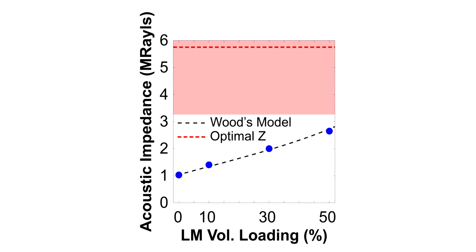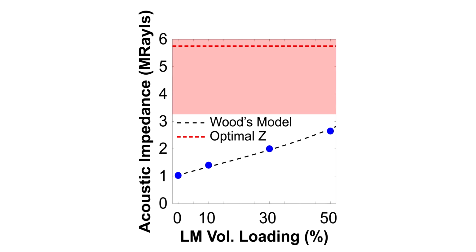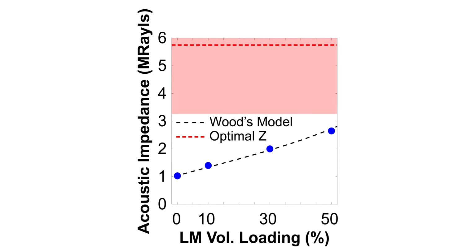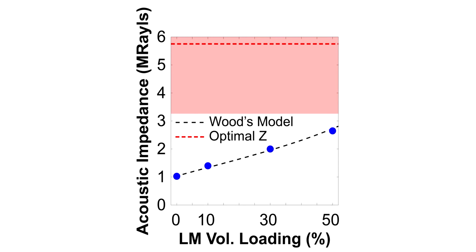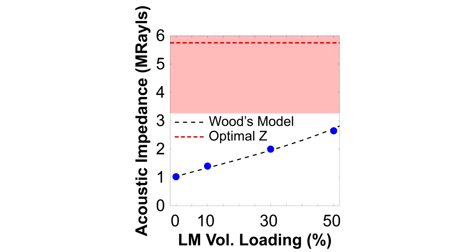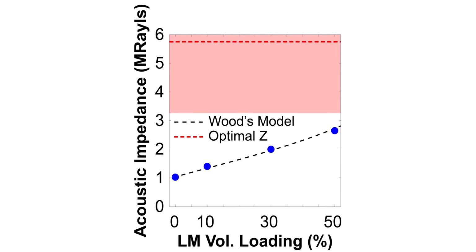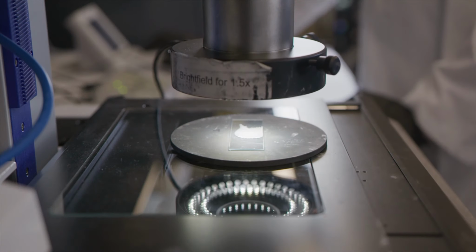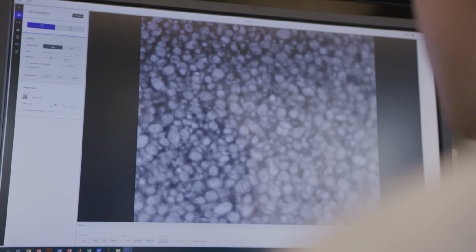The optimal acoustic impedance is shown by the red dashed line, and the shaded region denotes acoustic impedance values for which transmitted intensity is greater than 90% of the possible transmitted intensity. This initial study illustrates that the liquid metal composite offers an alternative to traditional ultrasound matching layers that is mechanically compatible with the human body and existing wearable ultrasound patches by providing a unique combination of high strain limit, low elastic modulus, and tunable acoustic impedance.